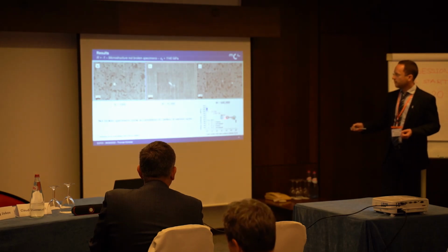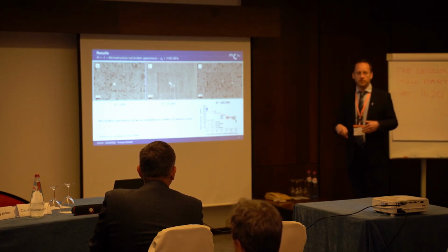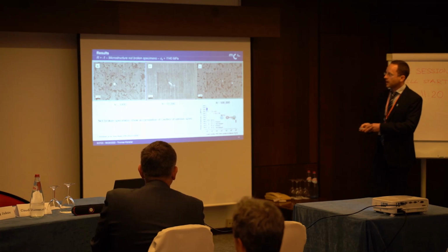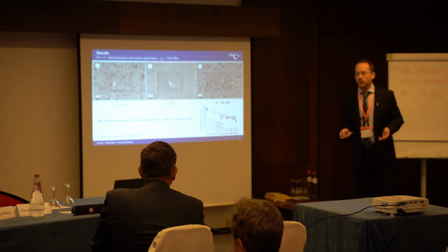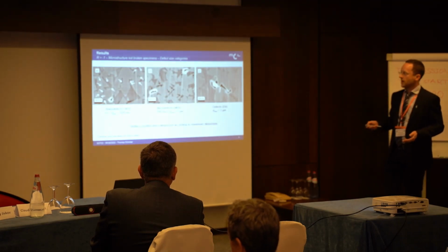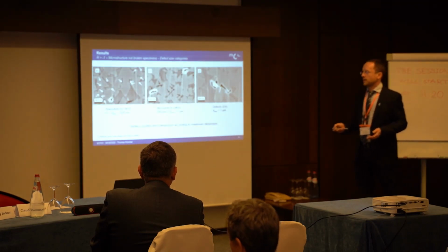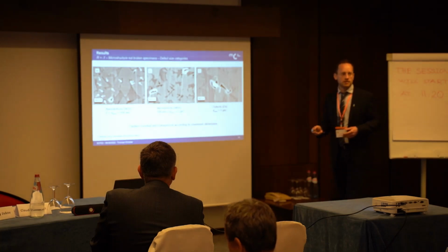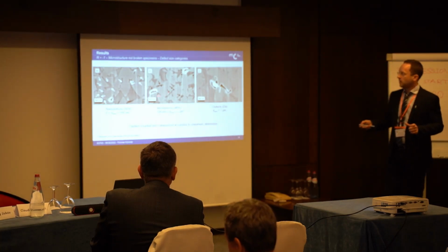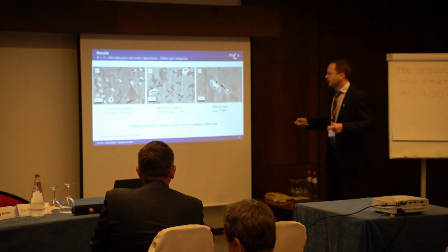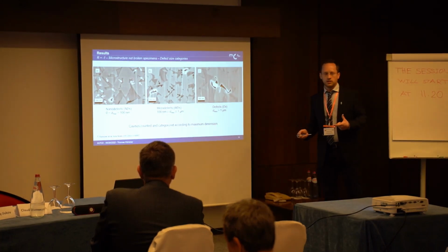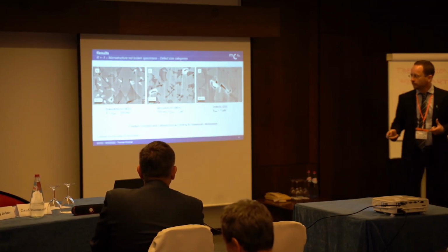We looked at unfractured specimens that we stopped before fracture, and what we see is, okay, we have a certain amount of small pores that have a certain size, right? We looked at the size of those, classified them. Now, defects in between 0 and 100 nanometers in maximum dimension or extension, micro defects that were in between 100 nanometers and 1 micrometer, and defects that were above 1 micrometer in size.